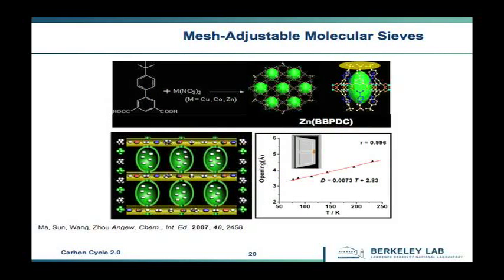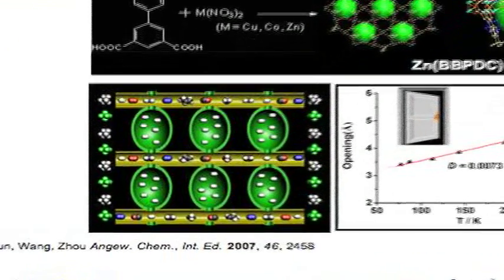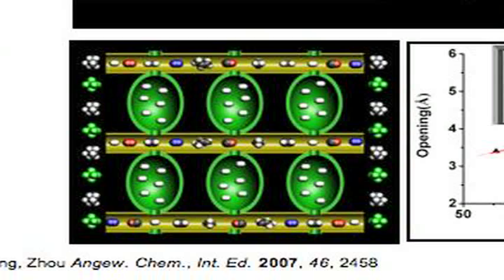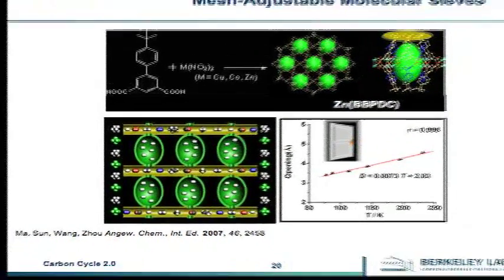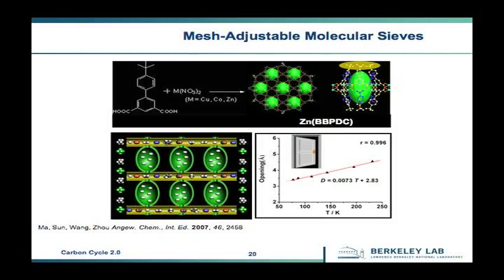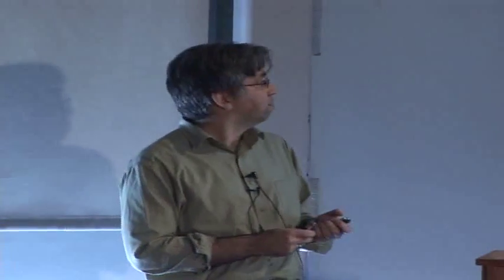At Texas A&M, they have a completely different approach. What they actually do is they make materials where, here you see a cavity where the gas molecules can be adsorbed, and the opening here can be made temperature dependent. So the idea is that you have those pores open or closed at exactly the moment where you would like to do this capture. So you capture at certain conditions and then you change the temperature in such a way that the pores open a little bit more so that the release is much easier. So the idea is that you can go through this capturing and regeneration cycle with far less energy, because it just requires a little bit of energy to open those pores and you don't have to heat the water.